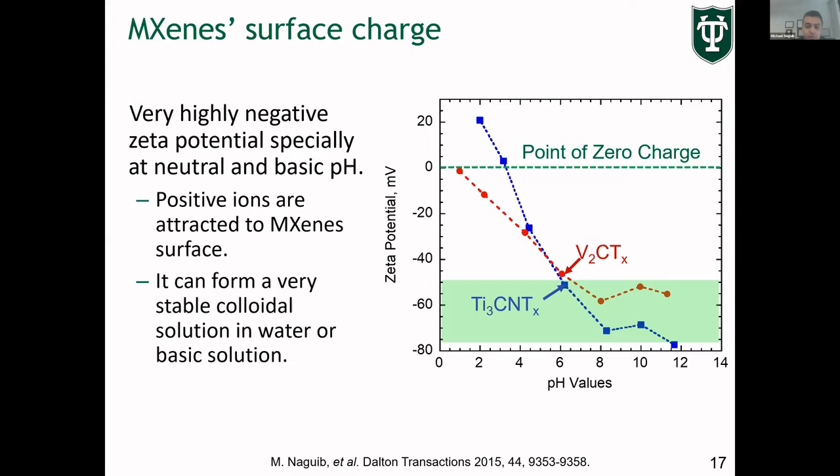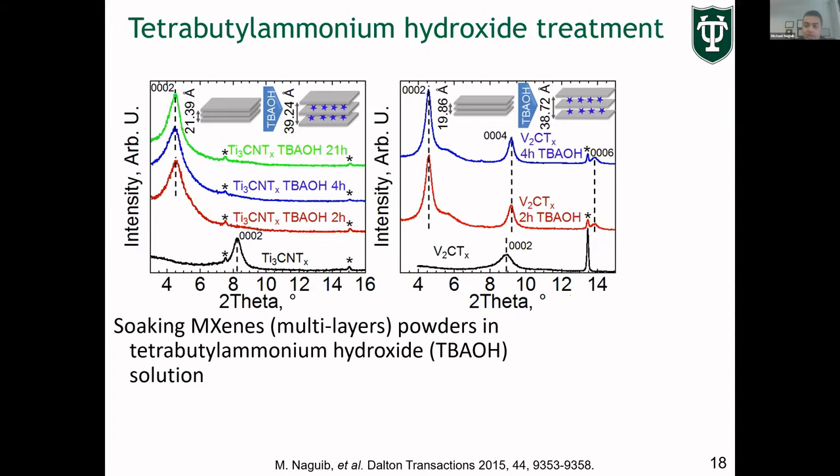Taking all these considerations together, MXene can be intercalated easily with cations, and they can also form a nice dispersion in water. So I decided, okay, let's use this information to enhance the processing and the delamination process. If you take Ti3C2 or V2C or many other MXenes and you put them in tetrabutylammonium hydroxide, for example, just after two hours there is a significant swelling in the lattice parameter, as you can see from the shift in the 0002 peak, and this increase in the c lattice parameter